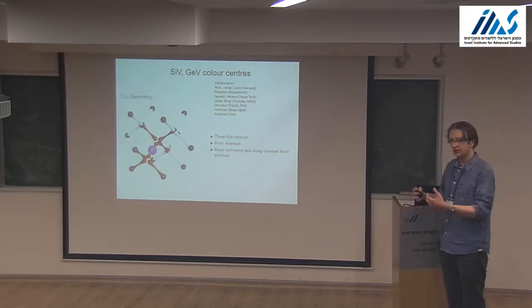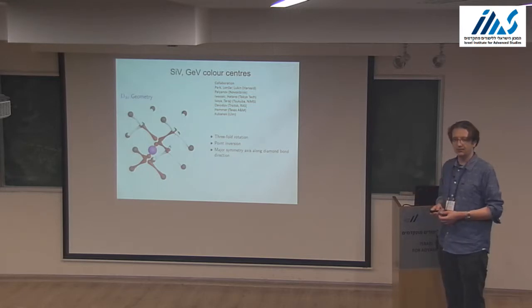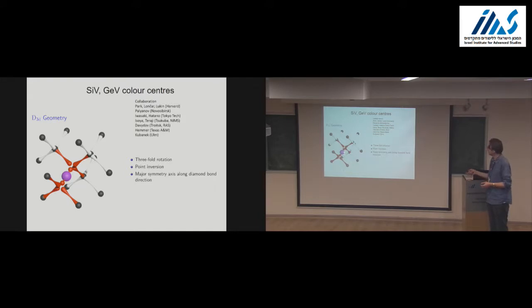It will start to get shifted and will sit between two vacancies, and that happens for silicon and germanium atomic impurities in diamond. So if you try to incorporate silicon or germanium in the diamond lattice, your silicon, which is significantly larger than carbon, will start to shift towards a vacancy, leaving a vacancy behind, and the structure essentially is an impurity atom sitting between two vacancies.